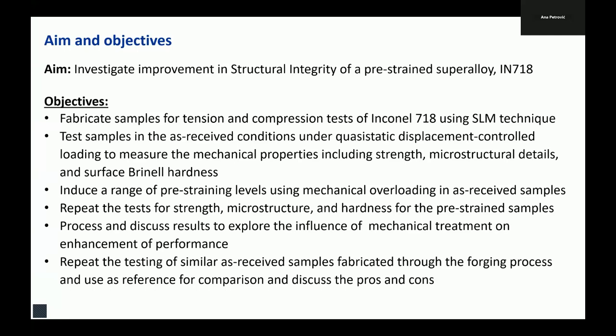So the aim is to investigate improvement in structural integrity of pre-strained superalloy Inconel 718, and the objective is, through fabrication of samples by this technique, and then extracting specimens, applying different levels of pre-strain on them, and then putting them into the tensile and compressive tests, to see how the impact is. Then look at the microstructure and see what sort of changes we can see, and if we can relate those to the improvements that we will hopefully see following this sort of treatment.